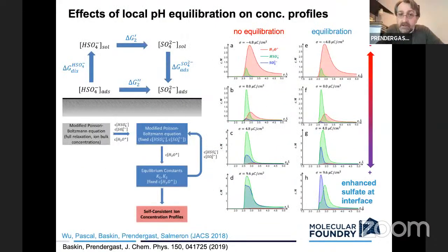Okay, good question. So the proxy for the pH here is the profile for the hydronium ion population. Okay, so let's say the starting solution has its own natural pH, which for sulfuric acid is going to be pretty low. But then you can see that the bulk pH would be, let's say, the limit of this red curve as it extends out to infinity. Okay, and so you can see also that pH is, let's see, these are different scales here, but it should be going to the same limit as you go outwards in distance. And then locally, you can see a strong enhancement of pH depending on the bias.